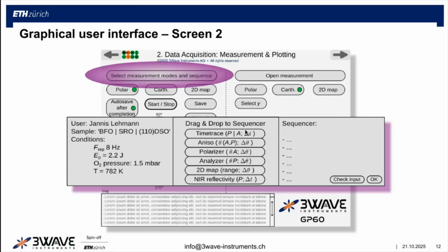Then after the growth, you might want to confirm with an anisotropy measurement how the distribution of domains looks or how your growth went. And therefore you can check the anisotropy. Here you can define a relative angle between the analyzer and polarizer and give an angular increment. And there's also a polarizer measurement where you only rotate the polarizer at a fixed analyzer position, and an analyzer measurement where you rotate the analyzer with a fixed polarizer position.